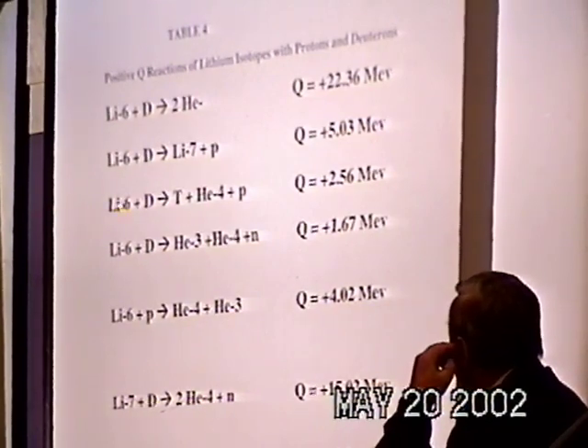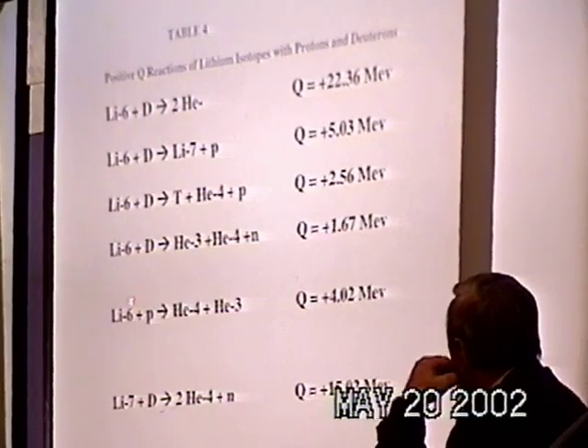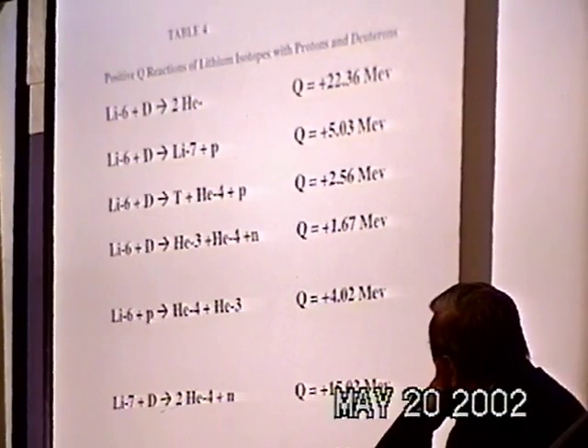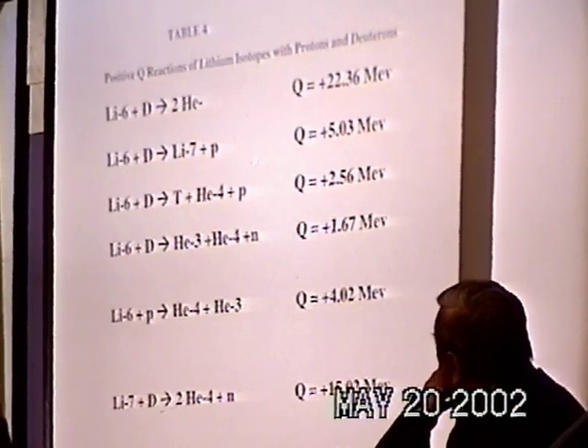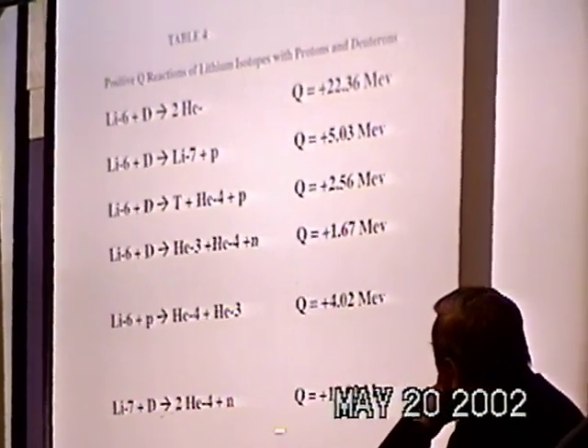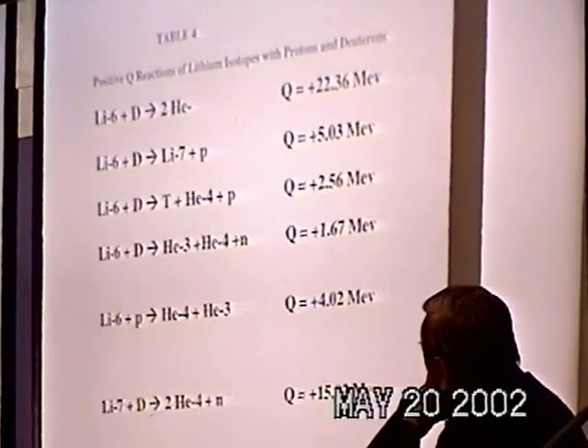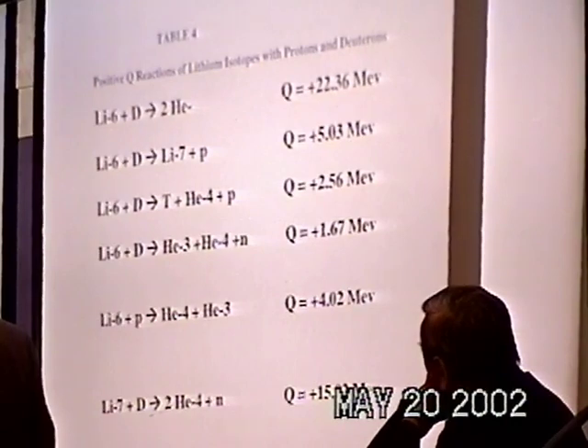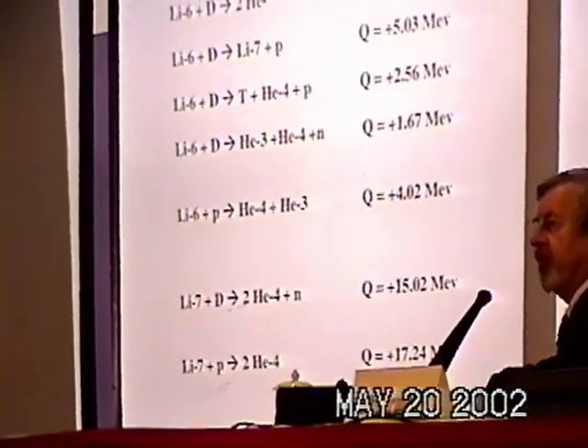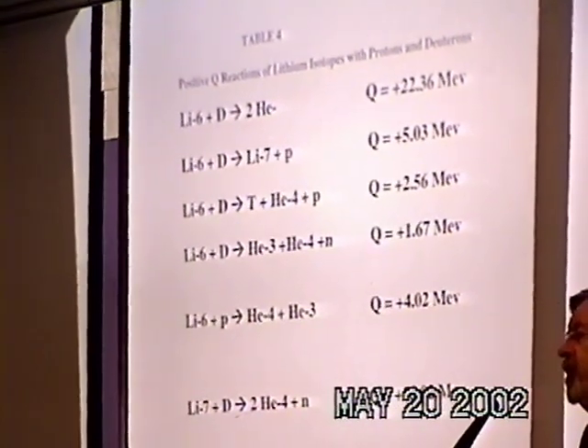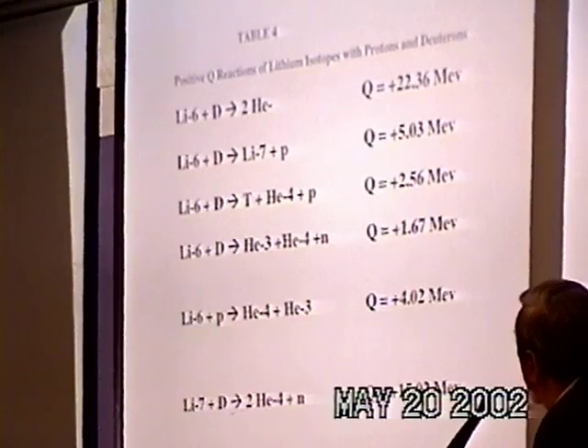We can make tritium also with lithium-6. These are all lithium-6 reactions. And notice we have 1, 2, 3, 4, 5 lithium-6 reactions and only 2 lithium-7 ones. And we're seeing depletion in 6 versus 7. Also, you can see the highest Q one is very similar to that of DD reaction, 24 MeV. So 22 MeV is a very substantial Q. Lithium-7 has a 15, and even protons give you 17 MeV with lithium-7. And I don't know why you wouldn't see some excess heat with protons, assuming that any of these reactions are possible. So I would not lose heart about looking for excess heat in samples that might be containing lithium.